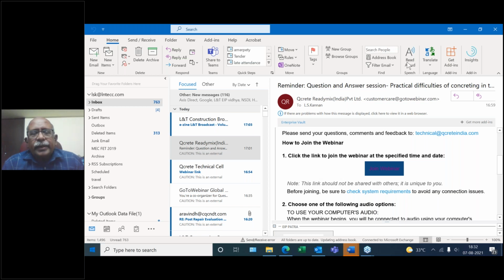Yes, sir. Please check the initial setting time of higher strength concrete. Normally when you admix a concrete, because without admixture we are not doing any concrete, the initial setting time of an admixture concrete will be around 5.5 to 6 hours. In case of an M30 or M40 grade concrete, when the grade goes more, even it goes up to 8 hours. So what you have to do is check the initial setting time of concrete, because the initial setting time is nothing but the so-called vibration limit, where you will be able to disturb the surface so that the stitching of concrete can happen. If you are able to stitch the old concrete and new concrete, then there is no question of cold joint.